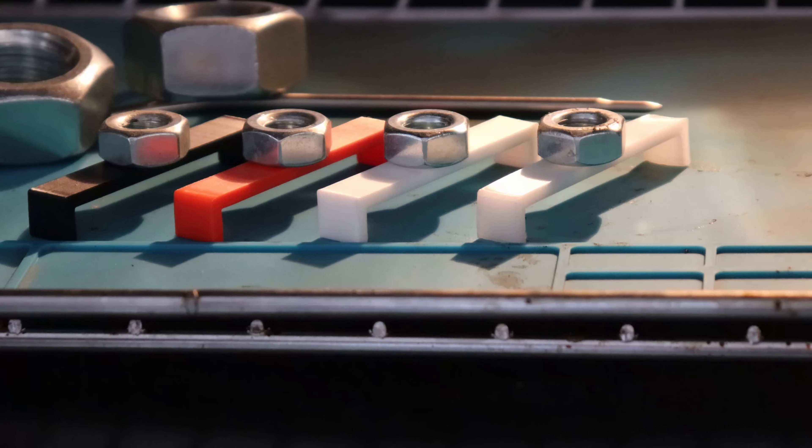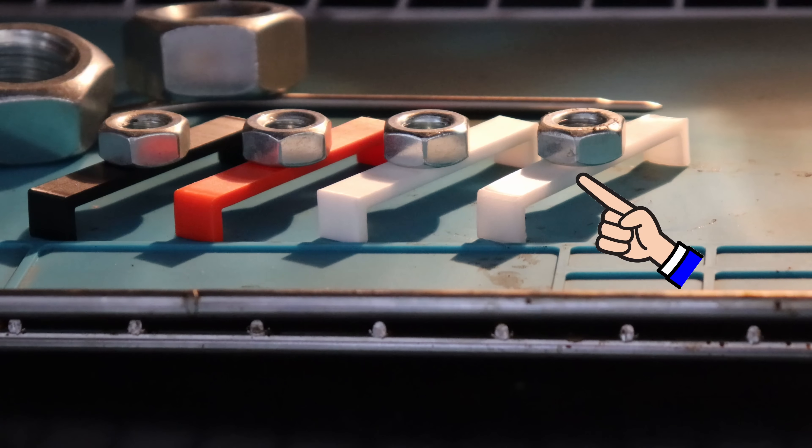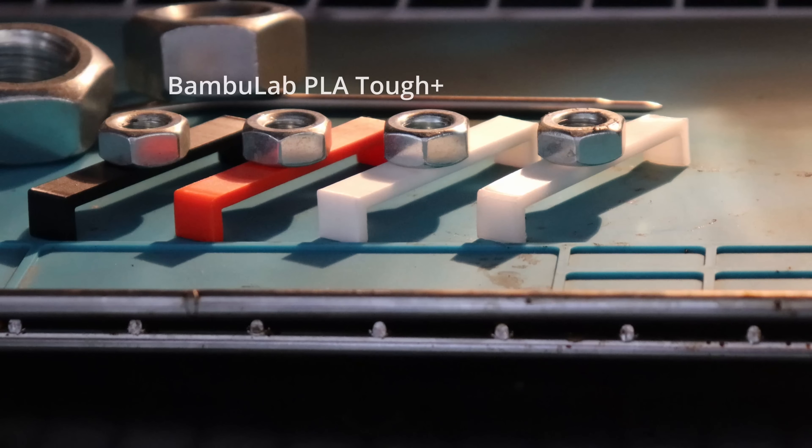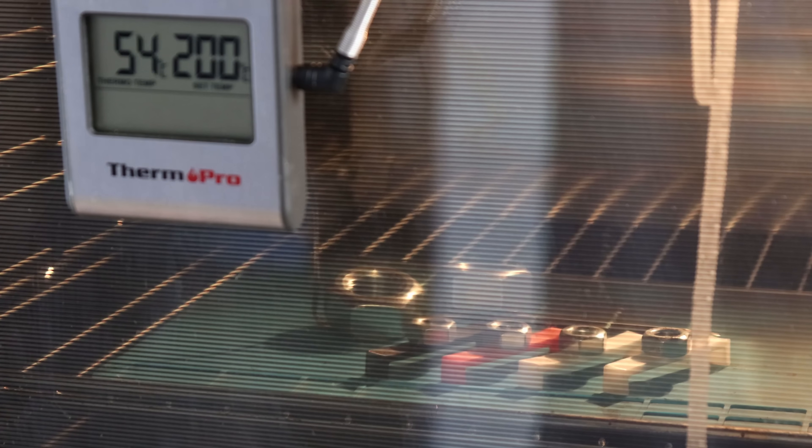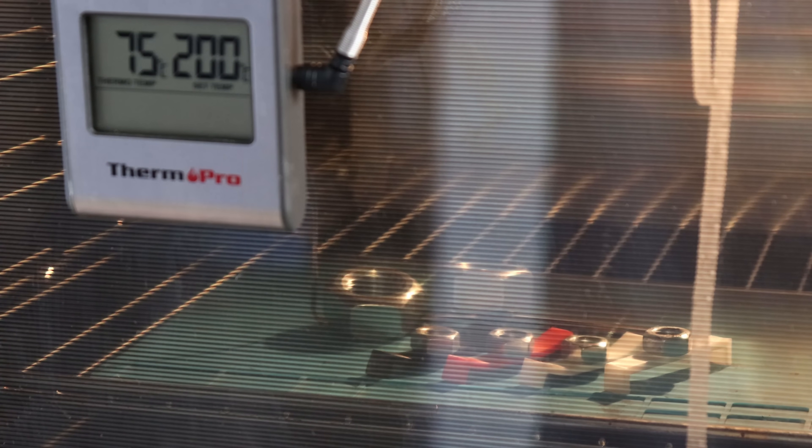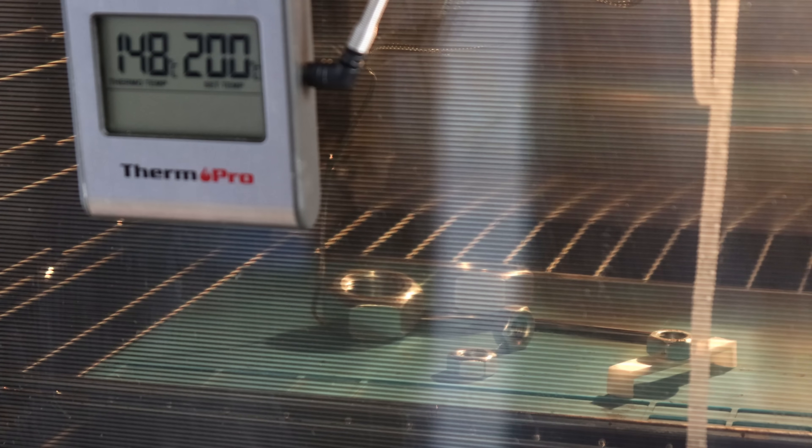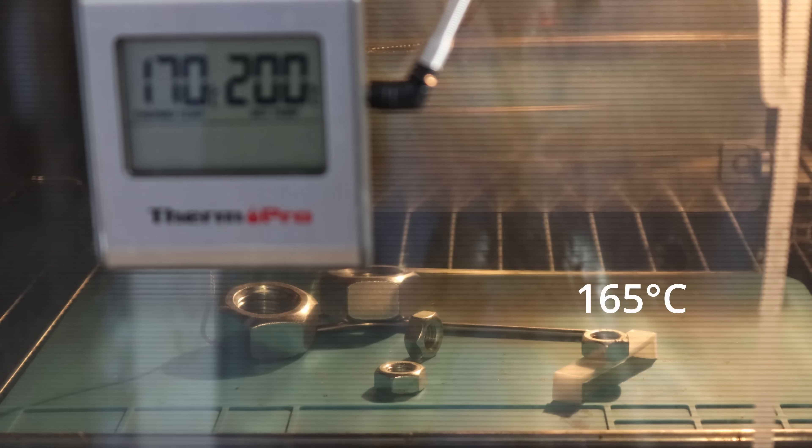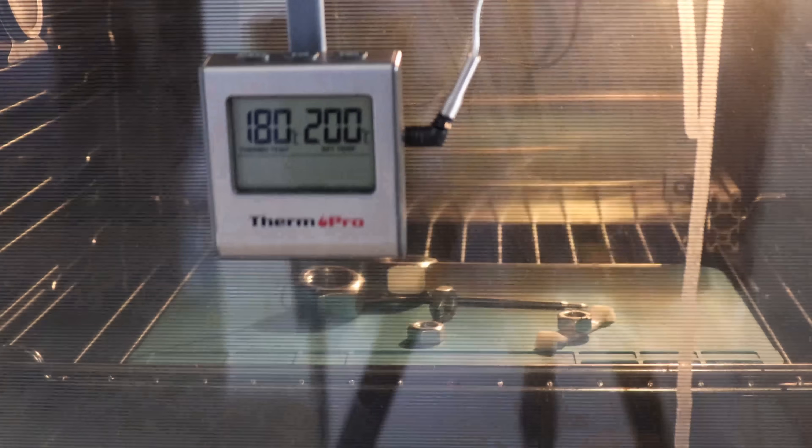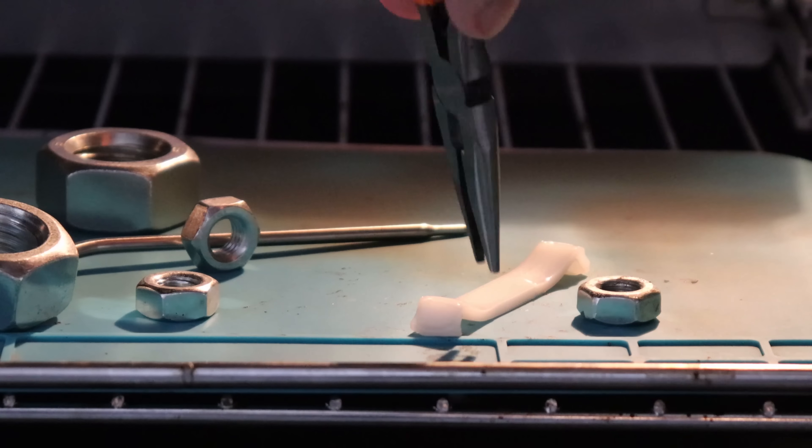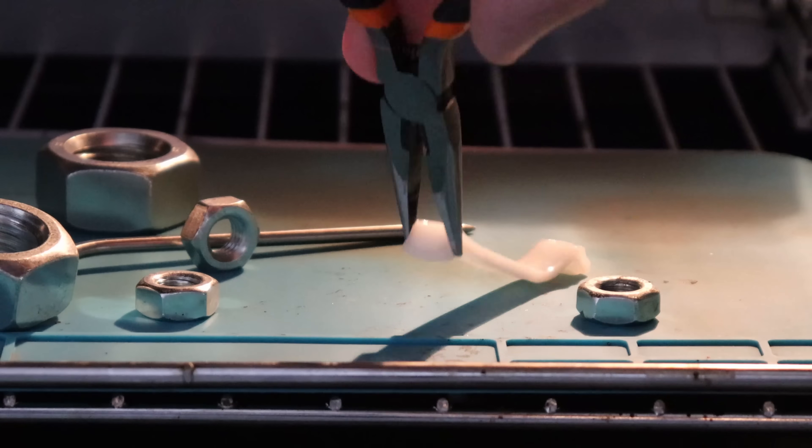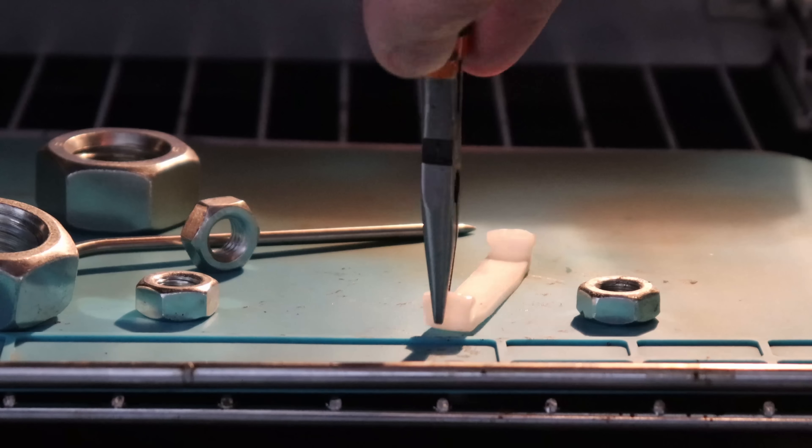Temperature test in the oven, and the last one on the right side is the filament from this video. 3 on the left are some PLA filaments which I will take out earlier. This is the beginning of the testing, PLA of course started to deform quite early, and I had to take them out, let's jump in the time. I didn't like this angle so I rotate the camera, just on time, and on 165 I noticed the deformation. Don't forget my testing is different from the ISO standard, here I have lighter loads, but at least my testing is same like I did in earlier videos, so the results are comparable with each other.